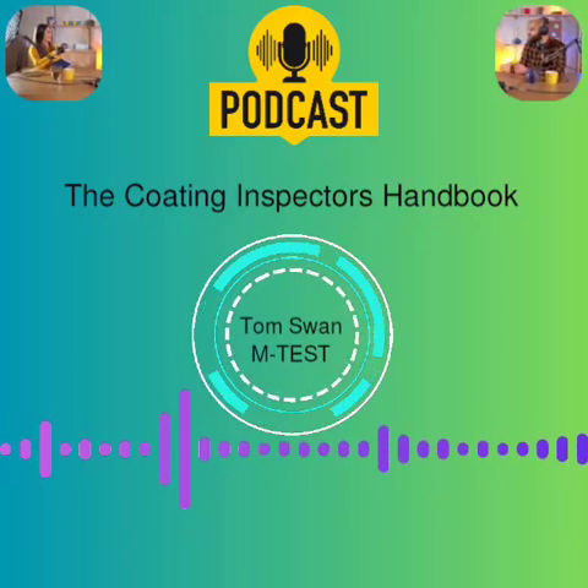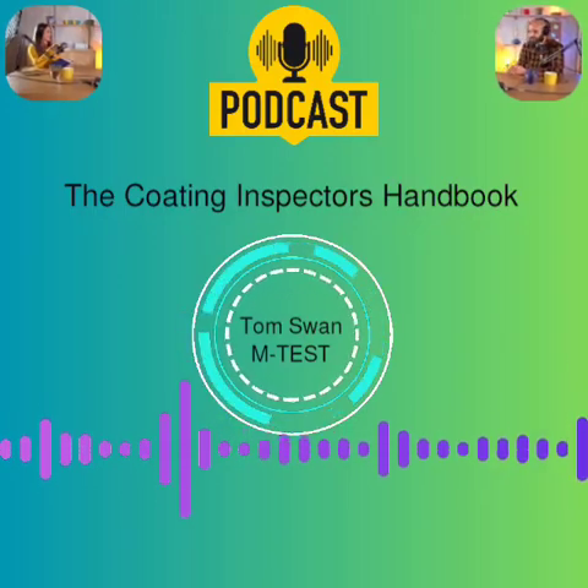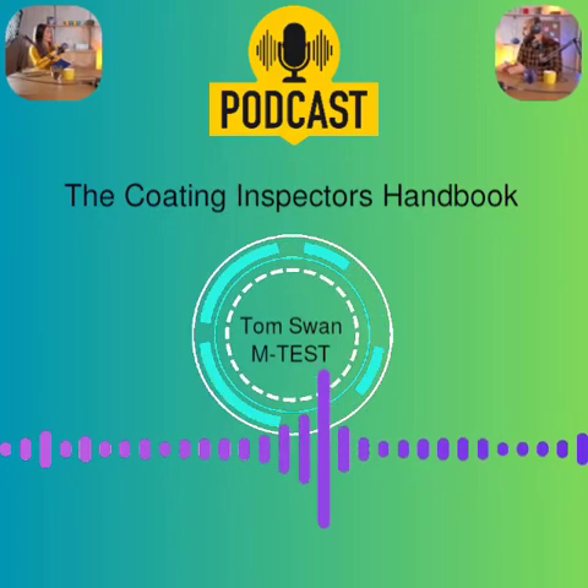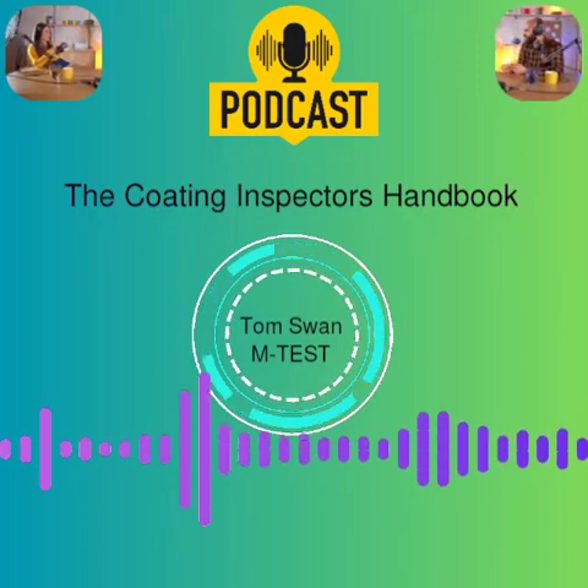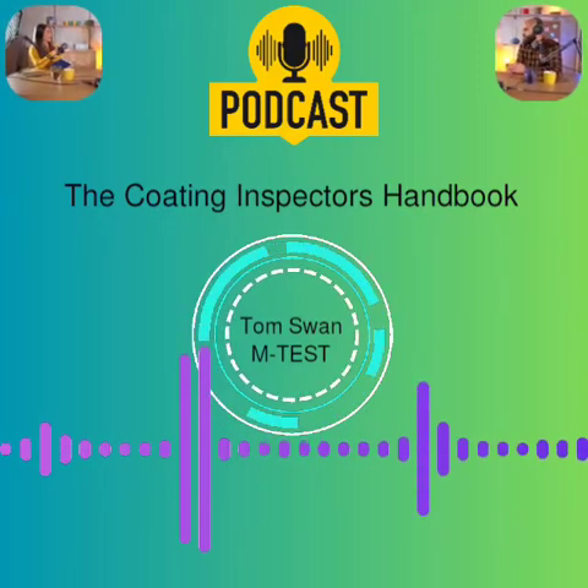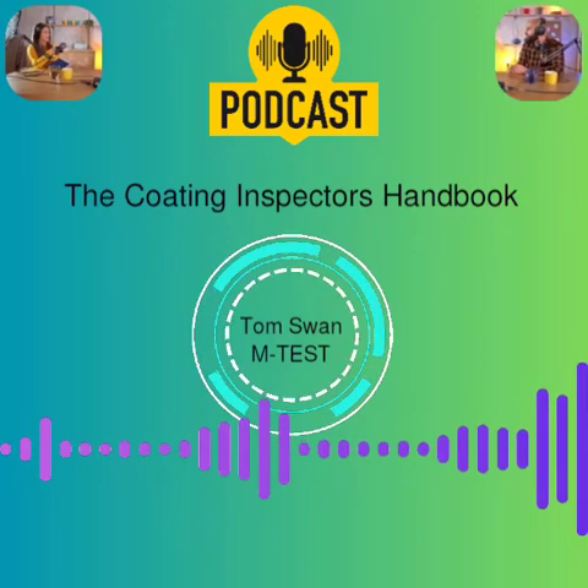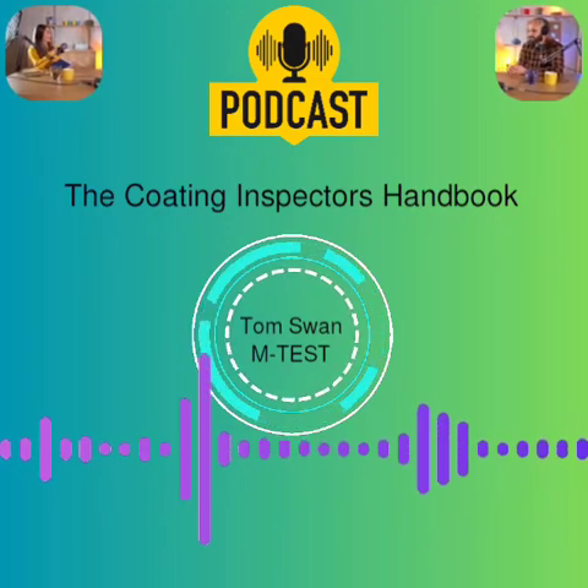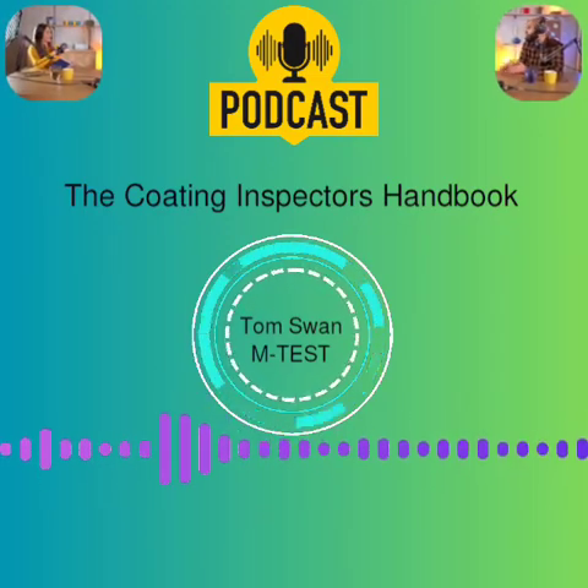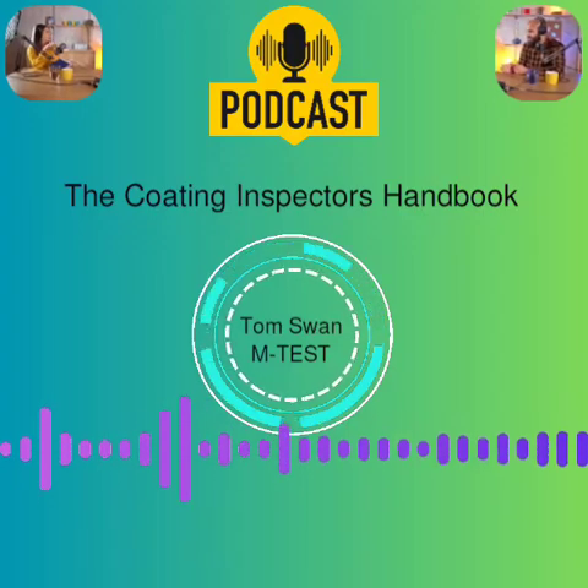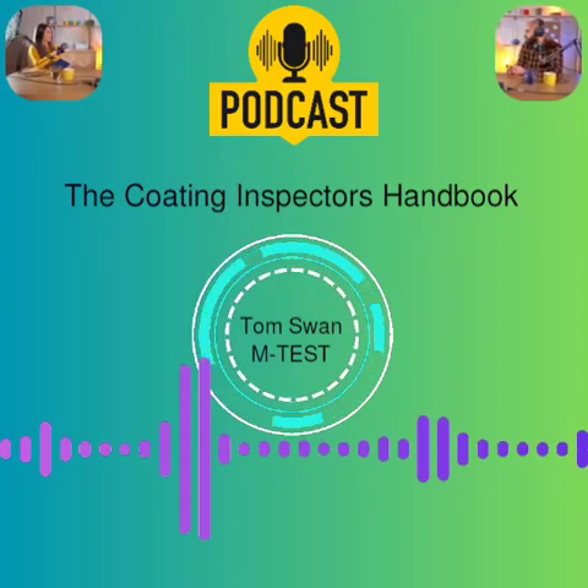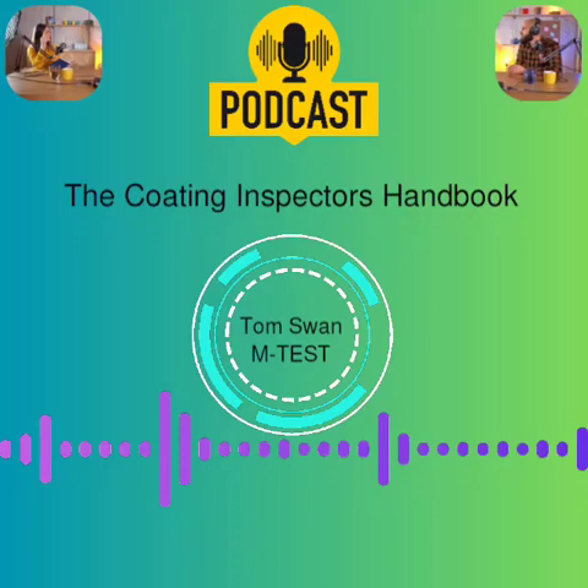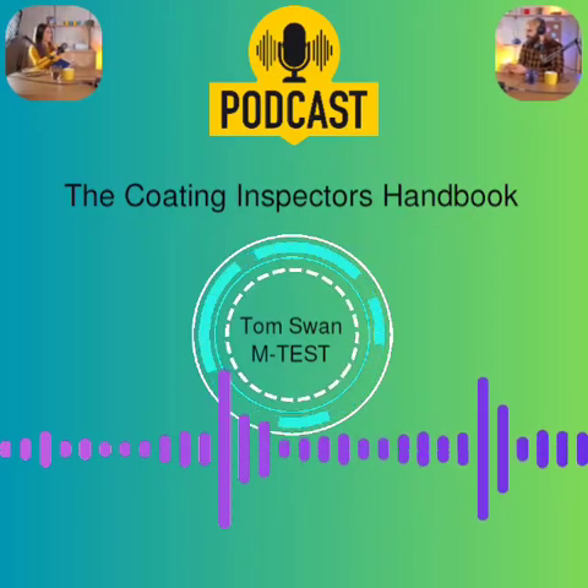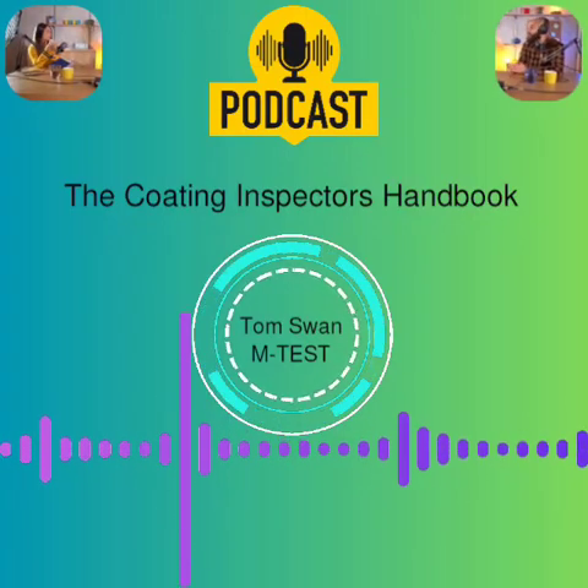Pros and cons of tape. Pro: you get a permanent physical record you can measure later. It's easy to do in the field. Less operator subjectivity in the measurement part. A con: it can get costly if you need lots of tests. The burnishing step is absolutely critical. If you don't rub hard enough, your reading will be too low. And the micrometer reads the thickest part of the impression, so it's closer to the maximum peak height, not the average depth. Using a wrong grade of tape or measuring it repeatedly also gives bad results.